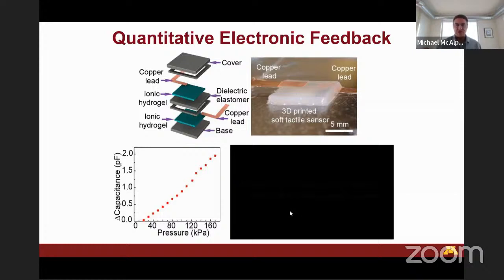There's one other difference, which is we use polyacrylamide, and then the ions that we use. Ziguang used sodium chloride, but we had to print this structure, and it takes some time to print it, so it can dry out. And so we switched to potassium chloride because it's hygroscopic, and it's sandwiched with a silicone dielectric in between, and then we put these copper leads on it. So this not only can act as an actuator like Ziguang showed, but also as a sensor.